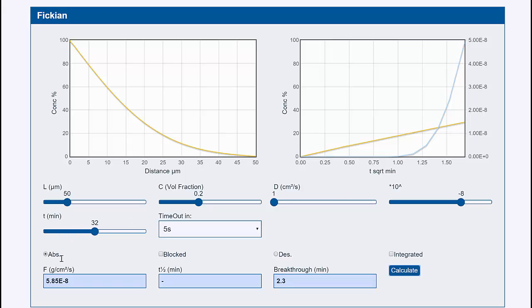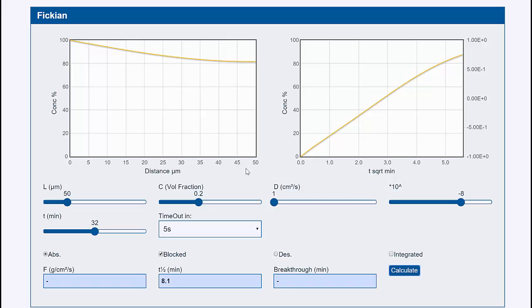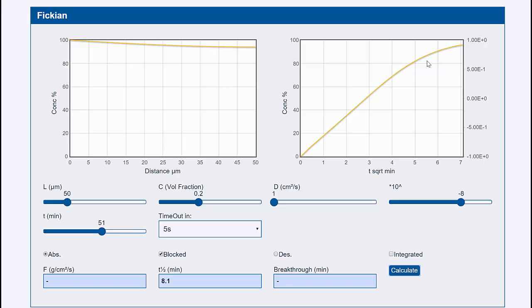Going back to the 30 minutes — this is looking at it in absorption, with the right-hand side open, so whatever comes to this side just disappears. If we block it and rerun it, of course nothing comes through, but we see the concentration builds up steadily, so we need more than 32 minutes. After 51 minutes we're getting pretty close. The half time is 8 minutes, so it takes 8 minutes to half-fill this.